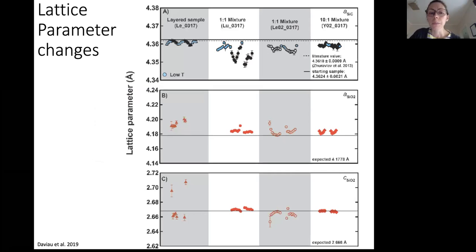But the other thing we observe, which is interesting: once we go through, we take our diffraction patterns, we get our quench patterns. I went through and found the volumes of silicon carbide and stishovite in all of these quench patterns. And what I observed was that there's actually some variation in the zero pressure volume. What I have plotted here is lattice parameter in angstroms on the y-axis. My top pattern is looking at the silicon carbide lattice parameter. These two bottom graphs are looking at the stishovite lattice parameter.